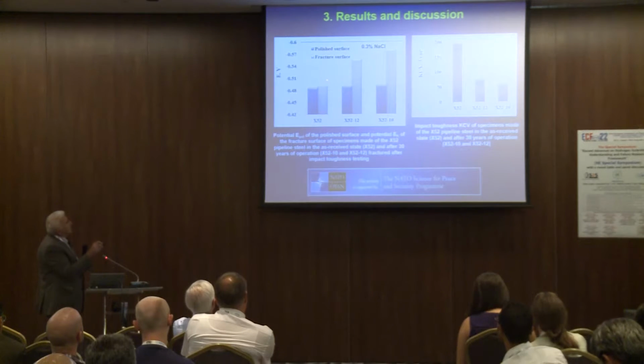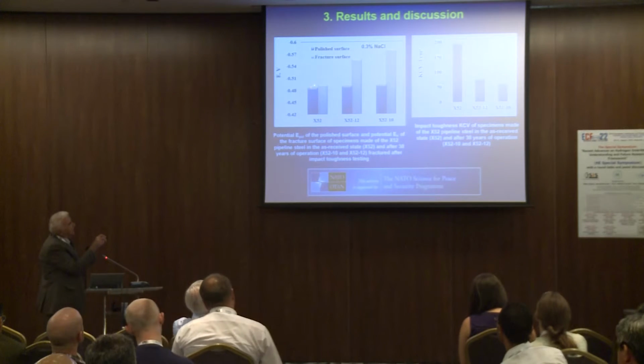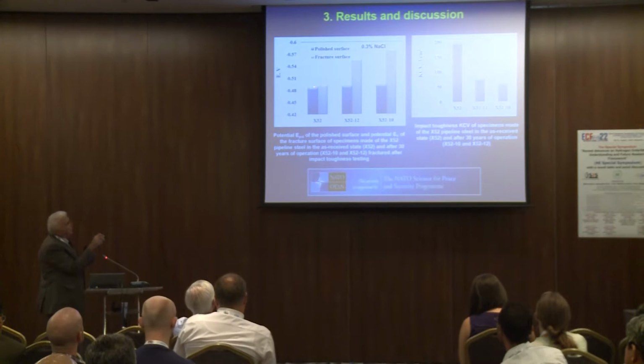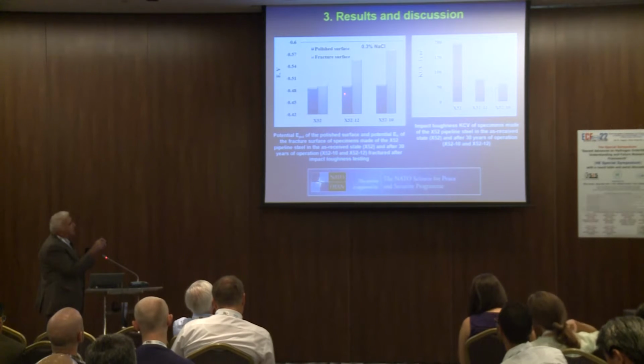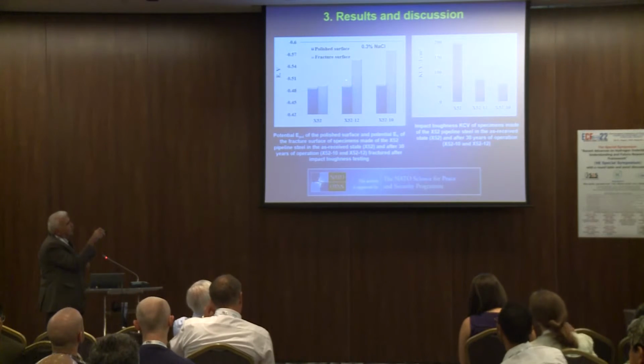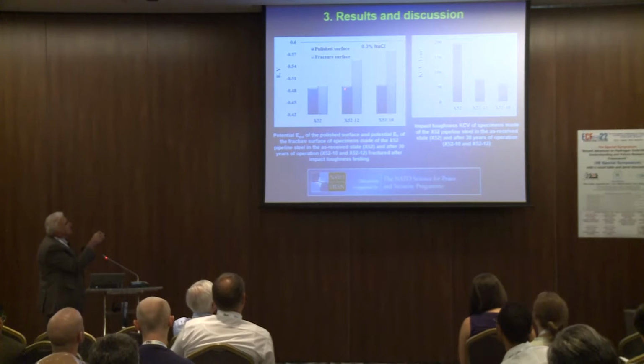If we compare the potential for the as-received state, we do not observe essential differences. But when we compare for exploited steels, you can see a big difference between the potential for polished metal, the typical potential, and the potential measured on the fracture surface.